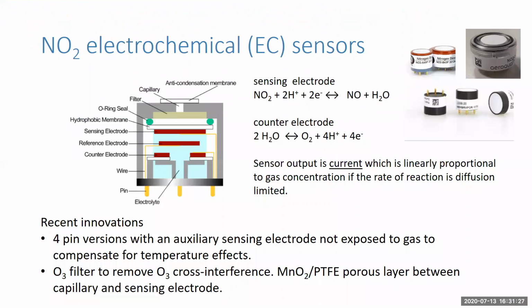The most common sensing technology for NO2 measurement is electrochemical gas sensors. And these are electrochemical cells in which the gas diffuses into the cell and reacts at the sensing electrode to generate a current. And it's the current that is measured in order to determine the NO2 concentration. Each of the cells usually contain about 3 electrodes. There's the working or sensing electrode in which the target gas reacts. There's a reference electrode and a counter electrode. And these are surrounded by an electrolyte, usually composed of sulfuric acid. The sensing electrode is usually coated with a catalyst to promote the sensing reaction.